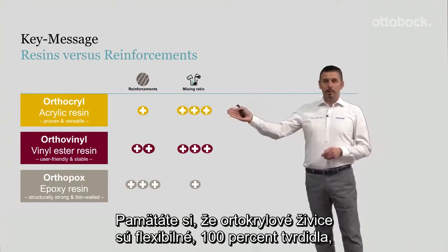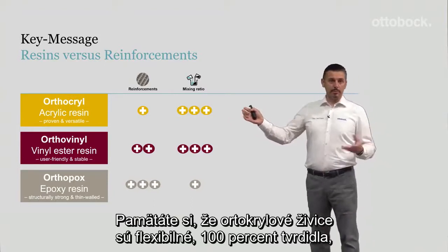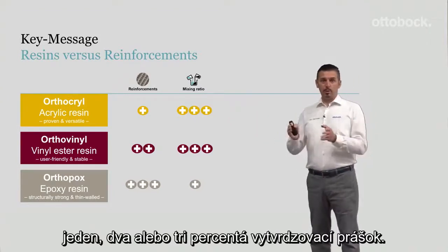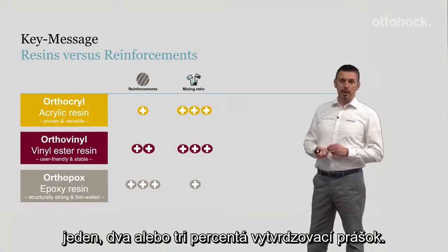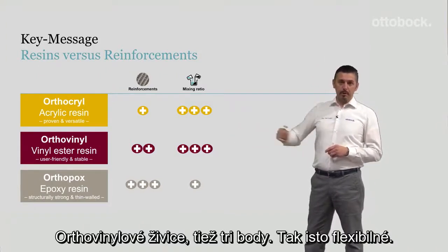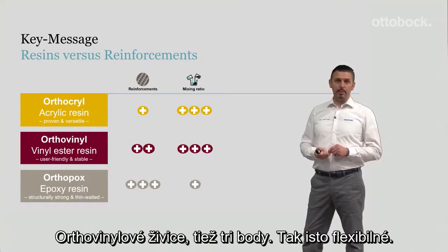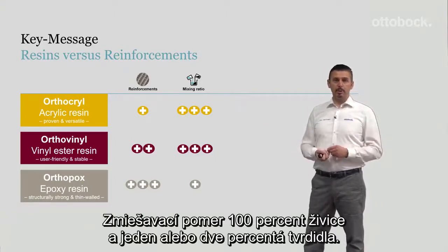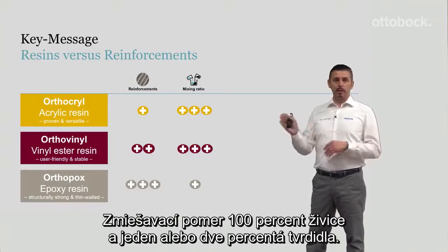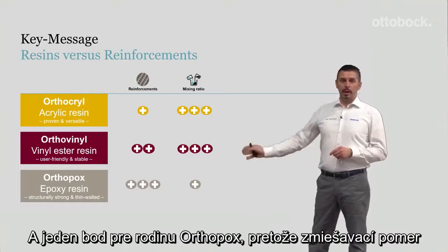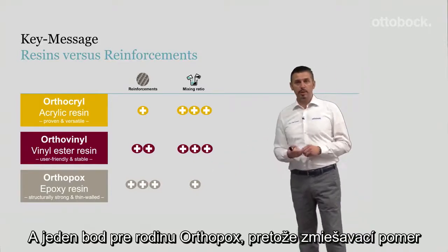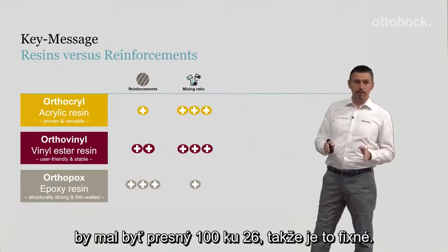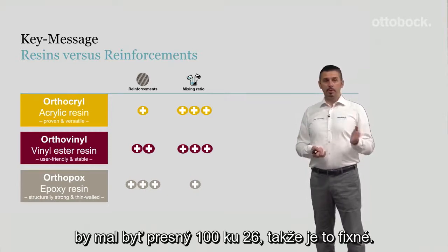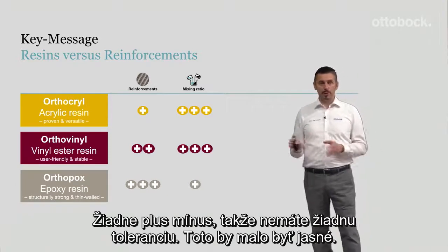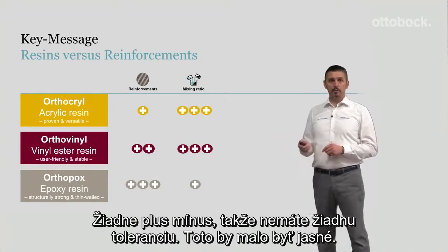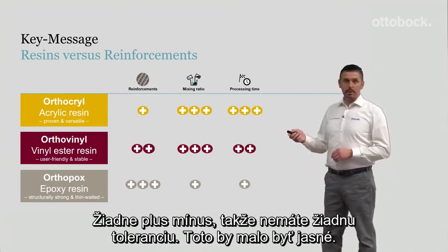Third one is the mixing ratio. You remember the orthocryl resins are flexible: 100% resin, 1, 2 or 3% of the hardening powder. The orthovinyl resin, 2 dots, flexible too, the mixing ratio 100% of the resin and 1 or 2% of the hardener. And 1 dot for the Orthopox family, because there it should be exactly the mixing ratio 100:26, so it's fixed. You have no chance to put plus minus, so you have no tolerance. That should be clear.